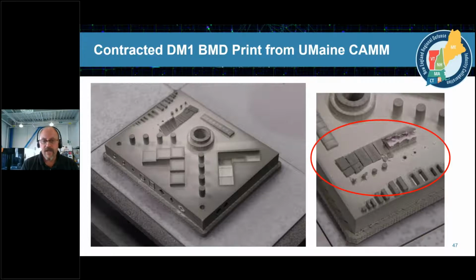With regard to the desktop metal machine, we had University of Maine print on their desktop metal 1 system. We have a metal 2 system. The difference in the desktop metal 1 to 2 system is that it requires a debinding phase, where you have to take the part after it's been printed, put it into a solvent debind system for a couple days, and then put it into a sintering furnace. What we encountered here with our system is you don't have to do that debind phase.